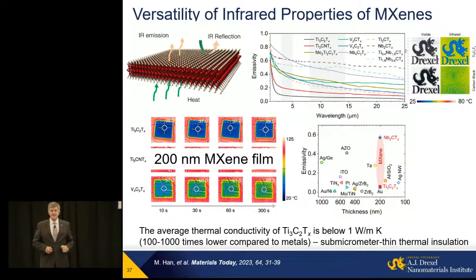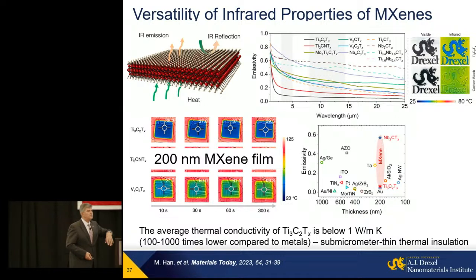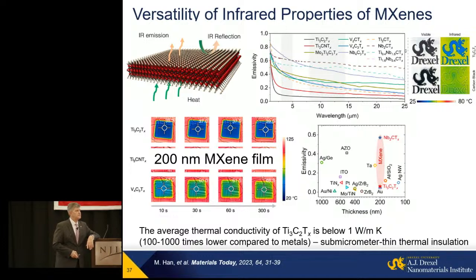Imagine painting every wall of a building with a material which is reflective in the infrared and has, unlike metals, thermal conductivity well below 1 watt per meter Kelvin. More than 1/3 of all energy we produce in the world is used by buildings. About 1/3 of this goes for heating and air conditioning. Imagine how big an impact it can be on heating the environment if we can have a paint that can really insulate and protect a building, minimizing the amount of energy we need to use for cooling and heating.